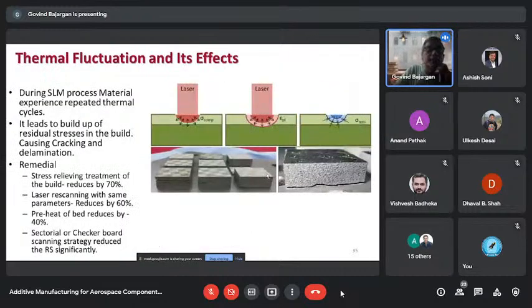So then there are thermal fluctuations. During SLM processes, we know that there is a repeated cycle: the material undergoes liquid, then solidification, then again the laser comes and melts part of the layer, or if it is not melted, then heat from the liquid above will be coming to this material. So there is thermal cycling, and it leads to residual stresses and build cracking. They are very common problems, and people have to struggle to resolve these issues.